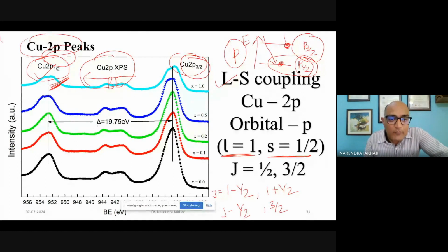And there is a gap of 19.75 electron volts between these two p peaks of copper. And this is the characteristic of copper: if you are getting two peaks, they are separated by 19.7 electron volts. So you can say that, okay, these are the copper peaks if the peaks are found around 950 electron volt. So in this way we are able to find out the different elements, their species, and so on.